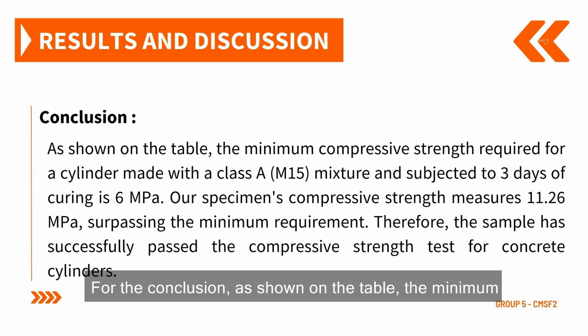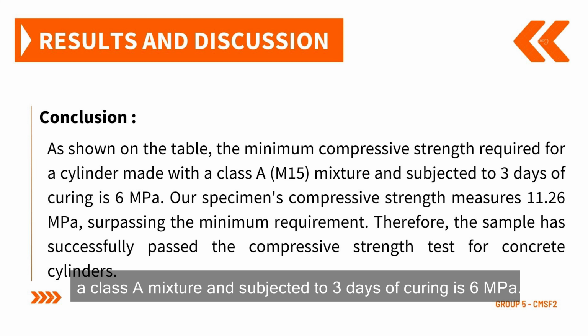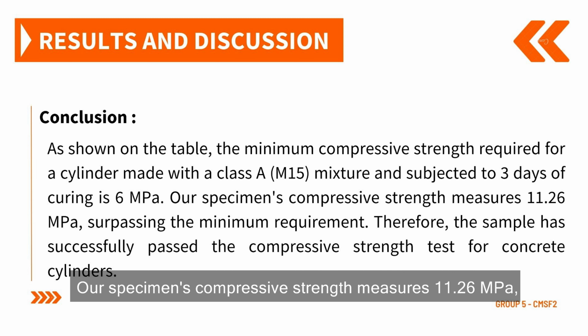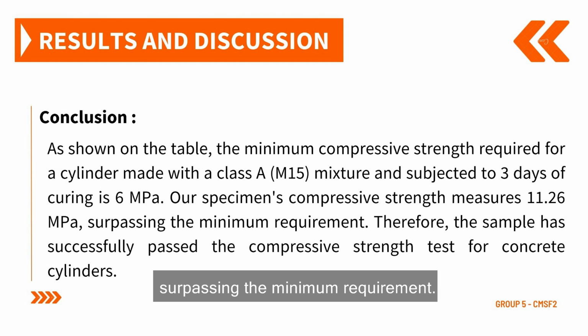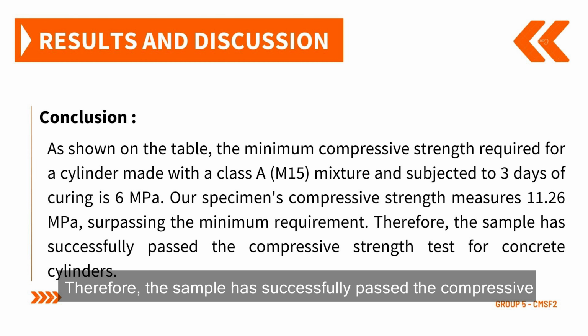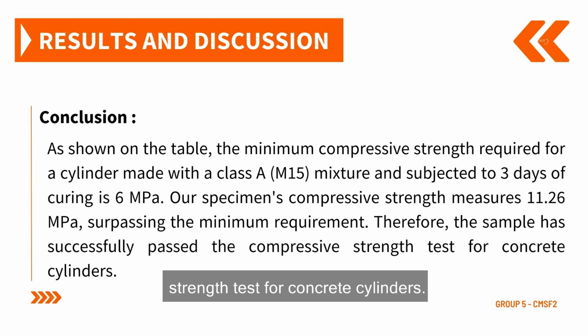For the conclusion, as shown on the table, the minimum compressive strength required for a cylinder made with a Class A mixture and subjected to 3 days of curing is 6 megapascals. Our specimen's compressive strength measures 11.26 megapascals, surpassing the minimum requirement. Therefore, the sample has successfully passed the compressive strength test for concrete cylinders.